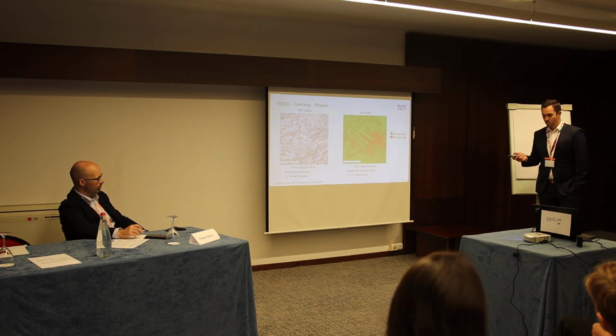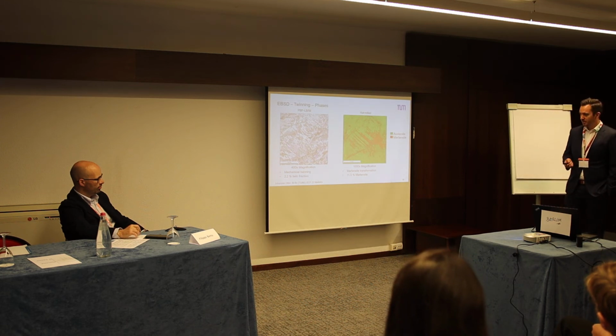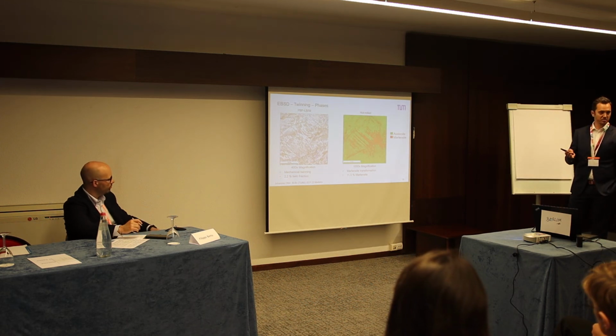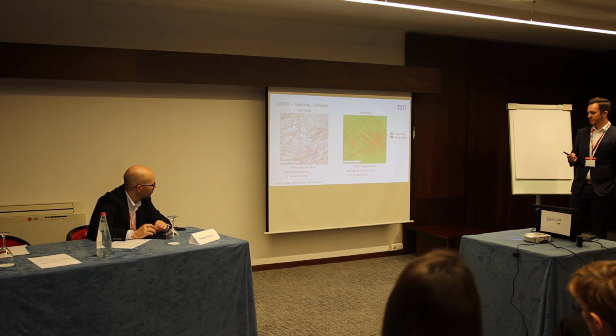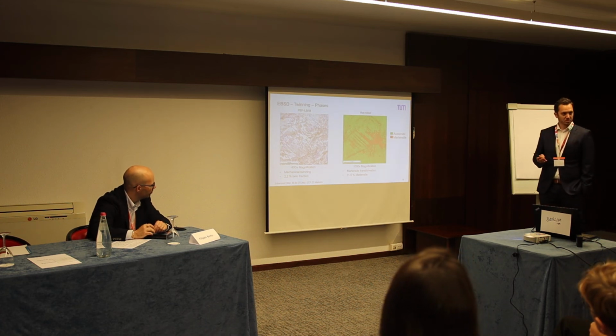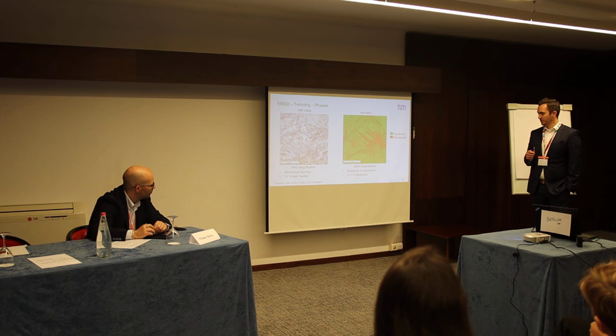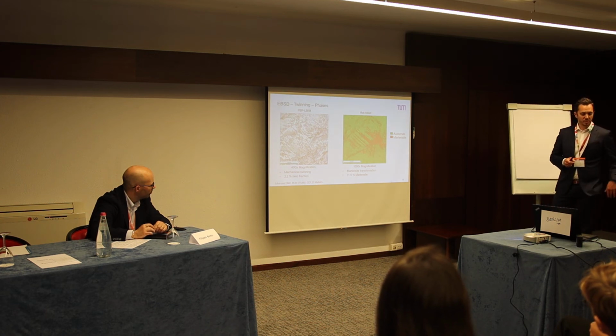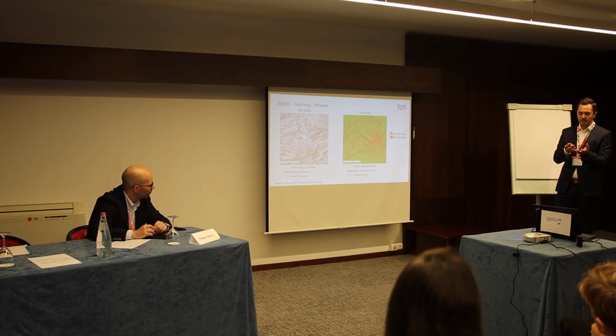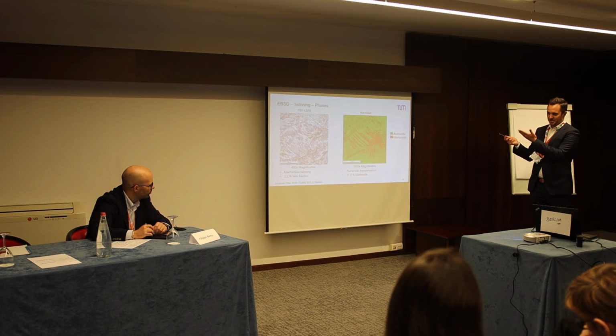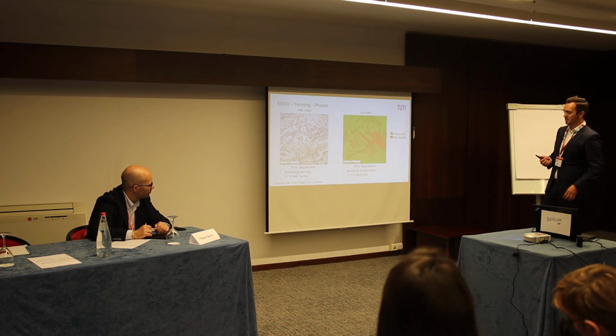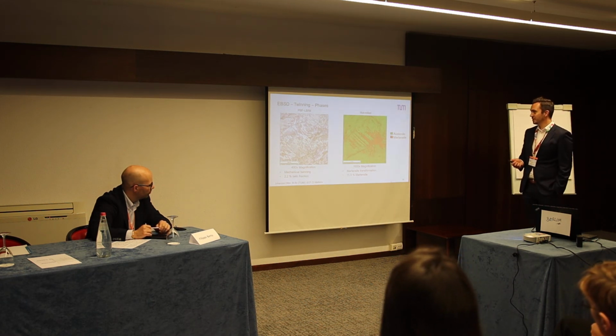For PBF-LB we couldn't find any difference, even though there was a small amount of ferrite or martensite measured with a ferrite scope. I guess it is because, and I will get to the results of that later, martensite can only grow inside a grain. Because of that, since we have such small grains in there, we cannot really measure it. At least our machine couldn't measure it. Probably there might be some, but we can discuss it later on.